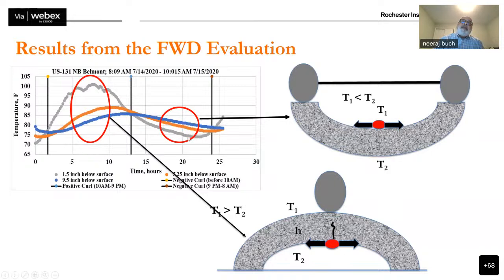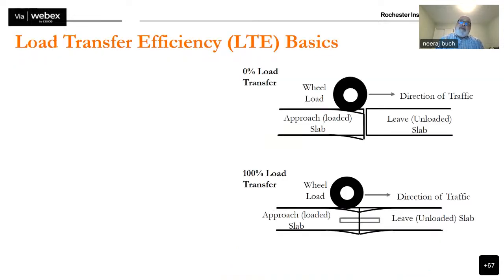Conversely, during the evening, you see a reversal in the temperature gradient. The gray line, the top of the slab, is cooler in the evening, whereas the blue line, at or close to the bottom of the slab, is hotter than the surface, and the slab was negatively curled. So what we have seen theoretically does happen in the field. It is important that you understand the relationship between deflection measurements and the geometric deformations of these concrete slabs. The other piece is load transfer efficiency.